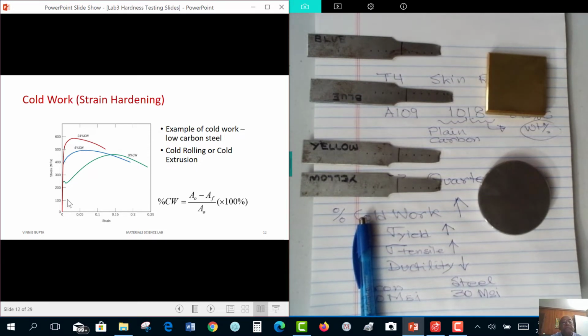So we have this low carbon steel. If it is in annealed state, that means 0% cold work, we see a very interesting phenomenon called yield point phenomenon. So I hope your professor in your lecture course would talk about it. This is the role carbon plays in iron. So in any case, you can see its yield strength is low. We give it a 4% cold work, we increase the yield strength from about 250 to nearly about 400. We go from 4% to 24%. We increase the yield strength from less than 400 to about 500.